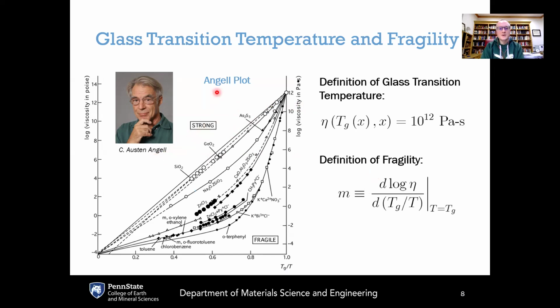He published this very famous Angell plot where he took the viscosity versus temperature curves for many different types of glass-forming liquids and plotted them all on this master plot here, where you have the logarithm of viscosity on the y-axis, and then a normalized inverse temperature on the x-axis, where it's normalized by this glass transition temperature Tg.